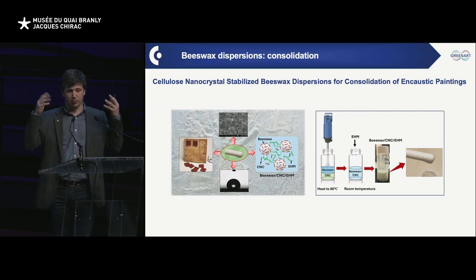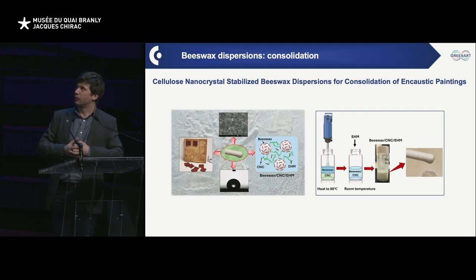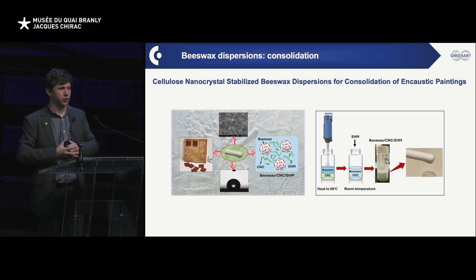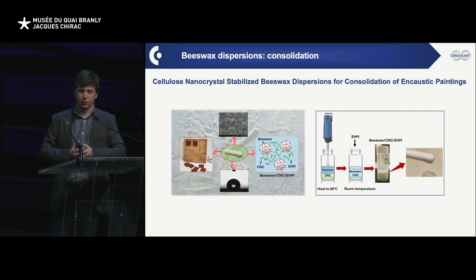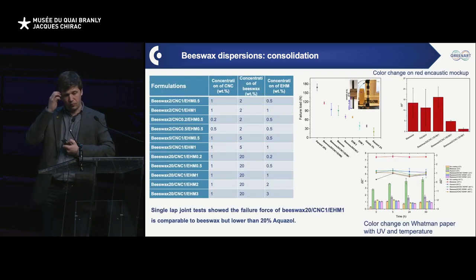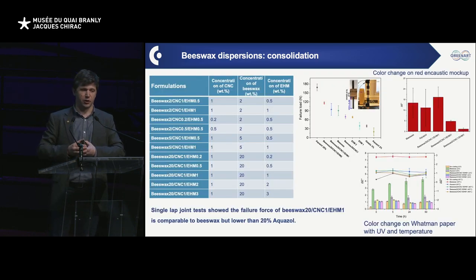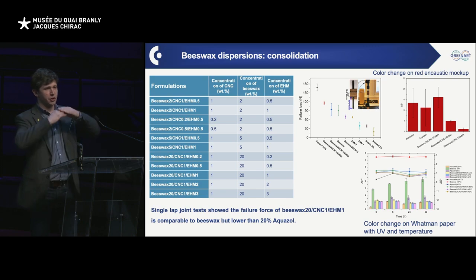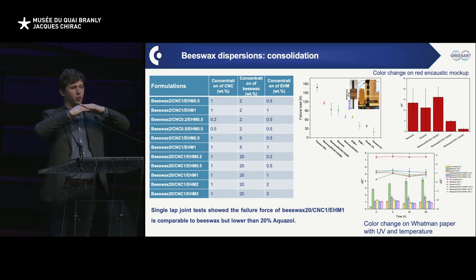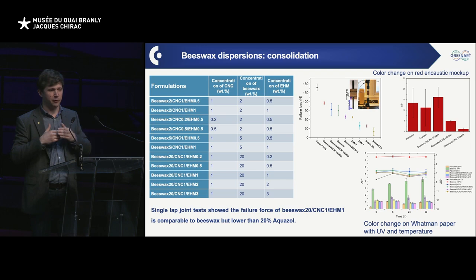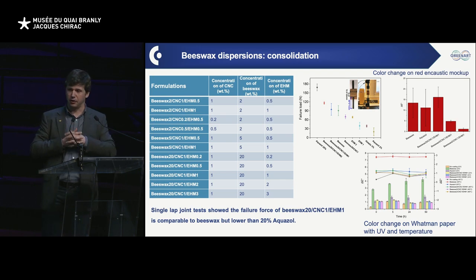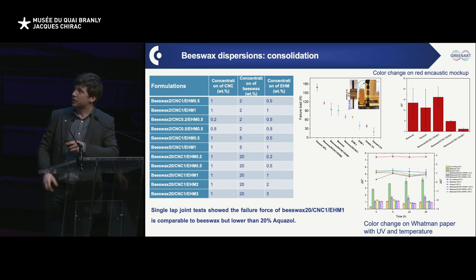So with that system in mind, we were pretty happy, and we thought, okay, now it's time to do something useful with it because we have been working on the emulsion, and let's see what we can do next. So the first type of testing was, okay, we developed that to glue encaustic paintings that are delaminating from a wood substrate. So let's see if we can use that as a decently good glue, essentially, because then we are playing with all the possible interactions at play, from hydrophilic to hydrophobic interactions. And this is what we did here.